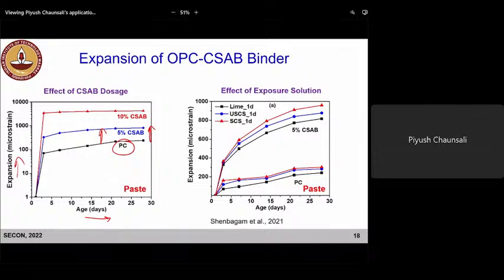And the curing environment also affects this. So we have seen in this case saturated lime curing versus undersaturated calcium sulfate. Let's say if we have an undersaturated gypsum solution versus a saturated gypsum solution, how does that affect it? We see that the saturated gypsum case led to increased expansion. So when the gypsum is saturated, when there is supersaturation, right? That is what we are saying: the exposure solution also affects the expansion.